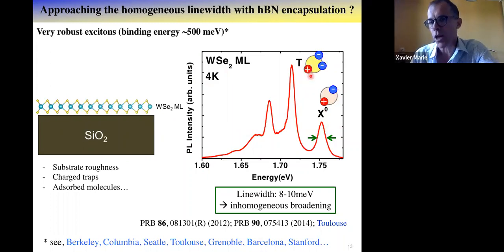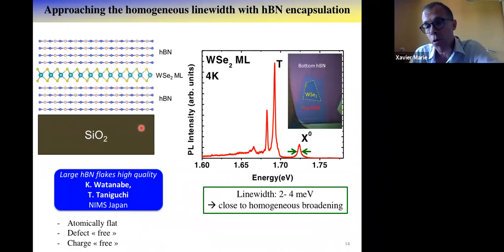This one is a charged exciton, trion, two electron, one hole, or two hole, one electron, whatever. But if you look at the line widths in photoluminescence or absorption, they're rather large, at least 8-10 millielectron volt or even larger. And it's due to the fact that you have this very inhomogeneous dielectric environment. And as for many groups, our life really changed when we progressed on the understanding of the properties, when we started to control this dielectric environment.